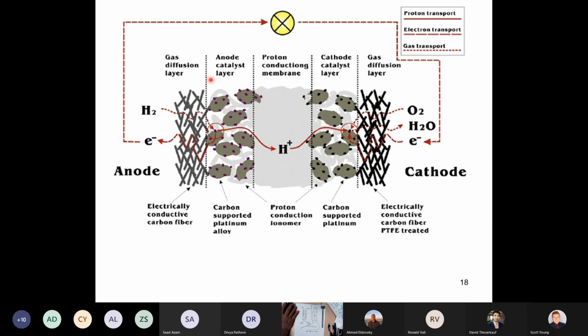So, let's talk about my experience with fuel cells. From about 2001 to, whenever Tim Crouch left the lab, maybe 2014 or 15, we had a fuel cell project with 3M on exactly this design, a polymer electrolyte membrane fuel cell. So we worked a lot on catalyst optimization, alloy catalysts, platinum nickel, platinum cobalt, platinum ruthenium, platinum anything, pretty much, even platinum silicon dioxide, for Pete's sake. And we also had a program on non-noble metal catalysts. So we made them by sputtering, by solution-based methods, all kinds of things. So I know something about fuel cells, so it's not like redox flow batteries where I don't know anything.